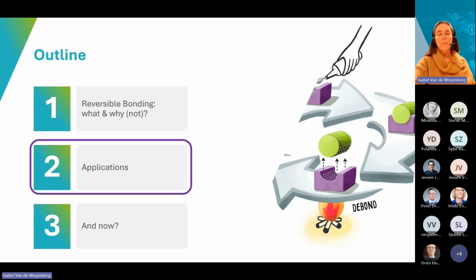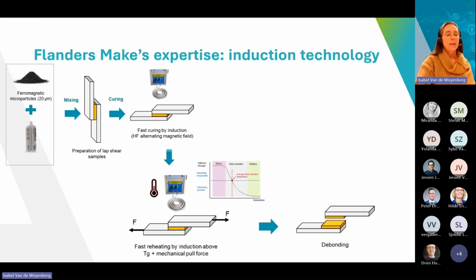So when we look at some real-life applications, some demonstrators, first of all, I want to explain a little bit the technologies that we will use. First of all, the induction technology. With an induction technology, we apply an electromagnetic field onto our components, onto our part. And if your substrate materials are not conductive, we can apply ferromagnetic particles to mix in our adhesive. And under an electromagnetic field, this adhesive will heat up in this way, will cure, so your bond becomes intact. It can also happen very fast. I will show this later on.